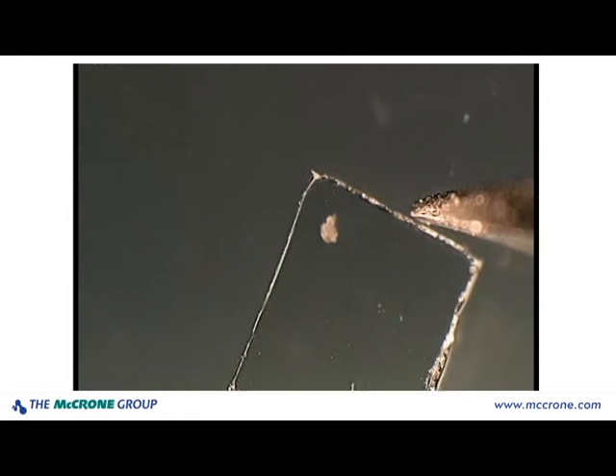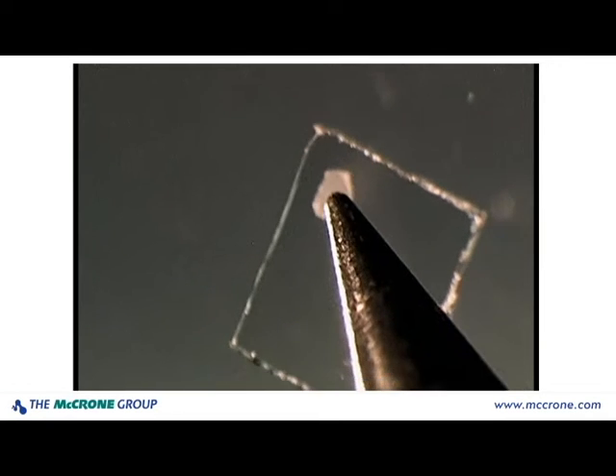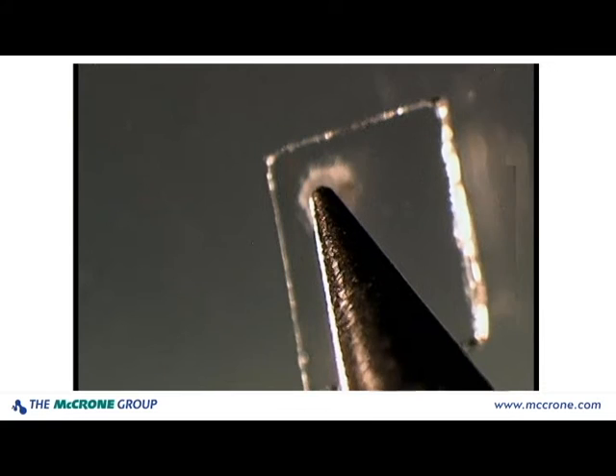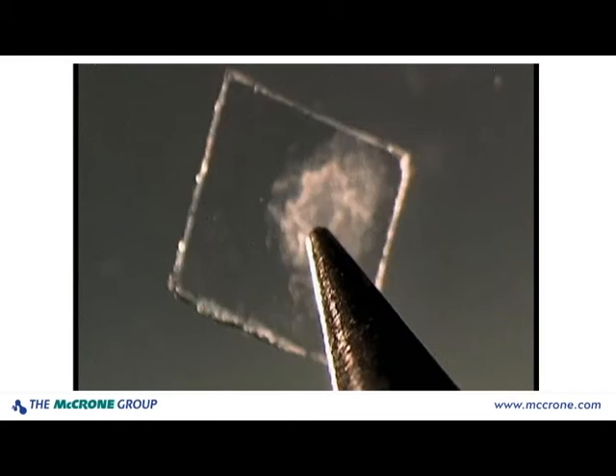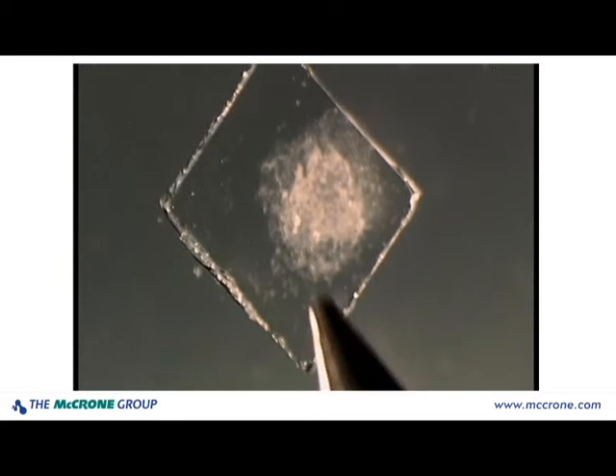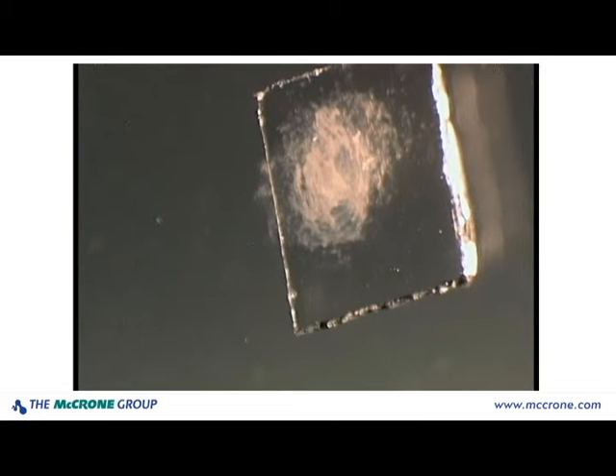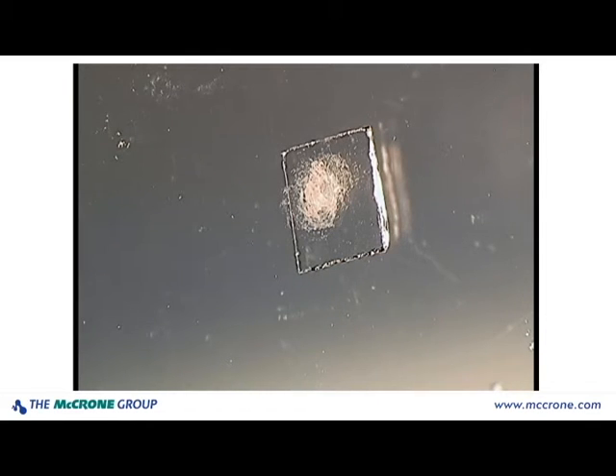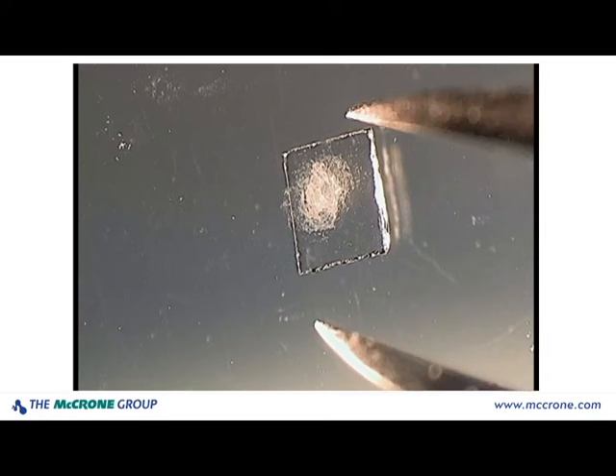I'm going to now use my curved forceps to place a micro cover glass over my sample, and using a carbide scribe, I'm going to apply pressure to the top of the glass and swirl the cover glass in a circular motion. By doing this, I'm breaking down the elastomeric properties and creating a very sticky residue. This residue should stick to the cover of the micro cover glass, allowing you to transfer it directly to the KBr. So now I'm going to come back in with my forceps, pick up the cover glass, and place it directly onto the micro KBr crystal.